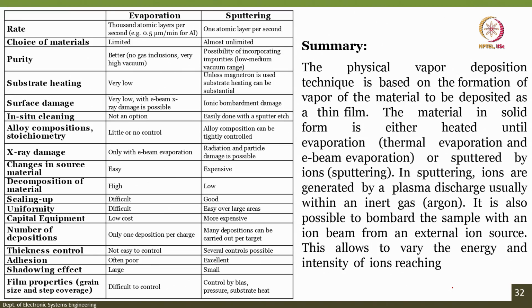That can be done. Next one is alloy composition and stoichiometry. So, there is little or no control because it is so fast, the atoms will not have time to rearrange themselves. But in case of sputtering, alloy composition can be tightly controlled. The next one is X-ray damage. Like I said, only with e-beam evaporation X-rays are generated, but radiation and particle damage is possible. However, X-ray is not really an issue because it is not generated in sputtering. Also, the radiation and particle damage may be one of the issues, but really not from the X-ray that is generated in case of e-beam. Changes in source material, it is easy for evaporation, you just have to load another material. In case of sputtering, it is a disk, so you have to change the disk with a new disk of that particular source. The scaling up of this system, evaporation is very difficult, while for sputtering it is comparatively easier.